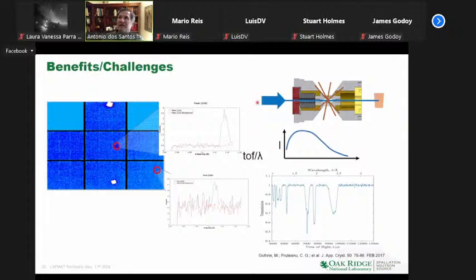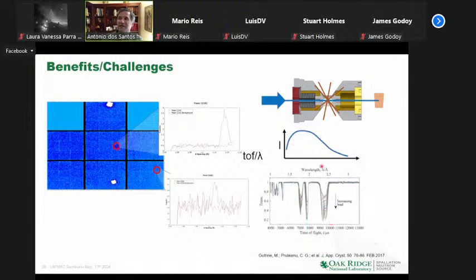One problem is that as the neutrons come, they go through this big single crystal, which basically monochromatizes some wavelengths of this incident spectrum of neutrons. And another problem is that as you increase pressure, the strain on the diamond changes, and so this almost removes completely any wavelengths like this. So it's very difficult to analyze this data as a function of pressure because you have to take into account this transmission data as a function of pressure, which has to be collected in situ, and that's why we have this monitor here.